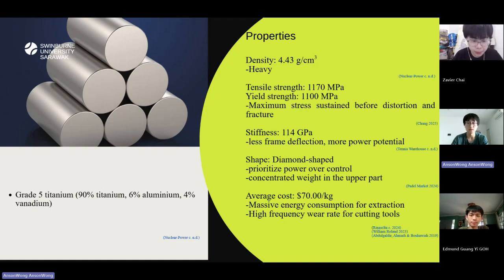The alloy offers a density of 4.43 grams per cubic centimeter, a tensile strength of 1,170 megapascal, a yield strength of 1,100 megapascal, and a stiffness of 114 gigapascal. As players, we are more focused on the yield strength as we don't want the frame to undergo permanent distortion or bending. The alloy is more suitable for a diamond-shaped racket, which prioritizes power over control by concentrating its weight in the upper parts. The average cost of the alloy is around $70 per kg.